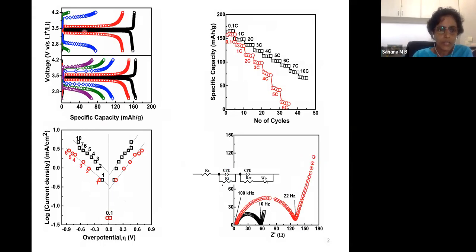The one on the top is where we added carbon black first and LiFePO4 next, which is a sequential mixing. And the down portion is where, I mean, first solid mixing happens. Carbon black is mixed with the LiFePO4. We can see here that when we pre-mix, the loss in the energy is very less. Loss in the energy, we basically see what is the difference in the voltage of charging and discharging.